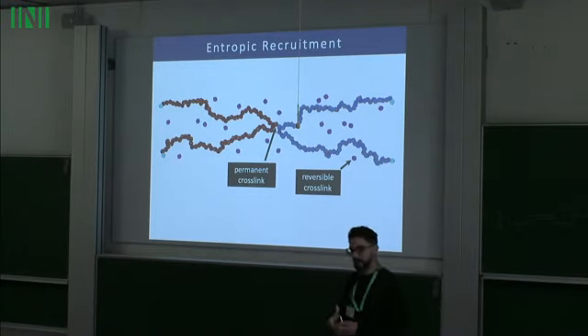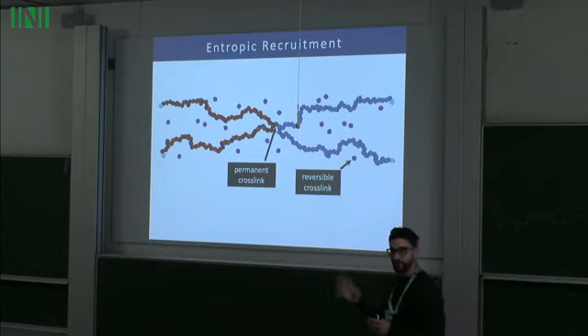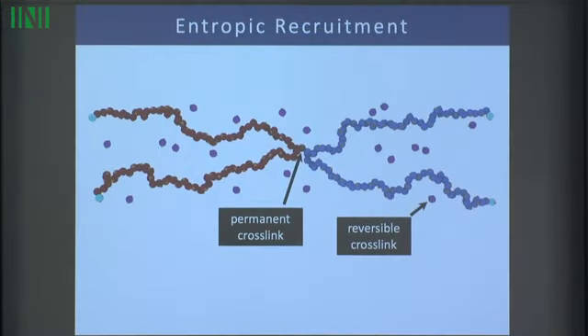So we just took another simple situation, but now in molecular dynamics simulation. We took these two polymer chains, the red and the blue. We permanently cross-link them by the brown bead and just fix that to the origin of the system. And then we put in reversible crosslinks, which is the purple things. And those can diffuse through the system. And they have, it's a bit hard to see, but they have little green binding eyeballs. And so they can form two bonds, and they form bonds with the little orange eyeballs on the polymer chains. Okay? So each monomer can hold one bond, and each reversible crosslink can make two bonds.